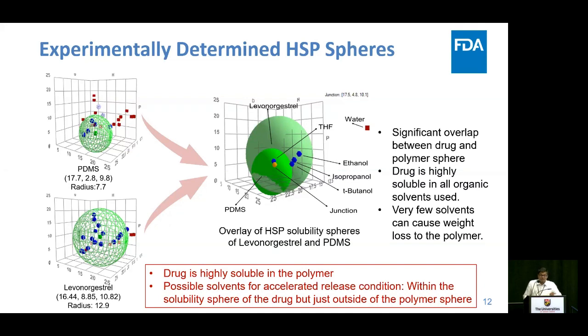We have previously seen that the release is dependent on partitioning of the drug, not solvent-mediated diffusion. So we need a solvent that will not swell the polymer itself, will not go through the polymer itself, but will have a high solubility of the drug. So a solvent should be just outside the polymer sphere, but within the solubility sphere of the drug. So isopropanol can be a good solvent, ethanol can be a good solvent, but THF cannot be a good solvent, because it will eventually go through the polymer, and then the release mechanism will change from solvent partitioning to solvent-mediated diffusion.